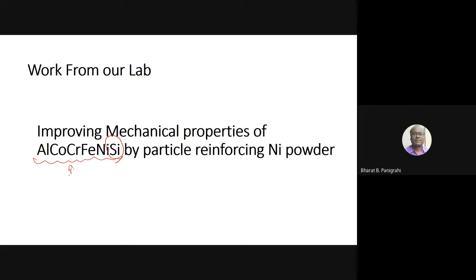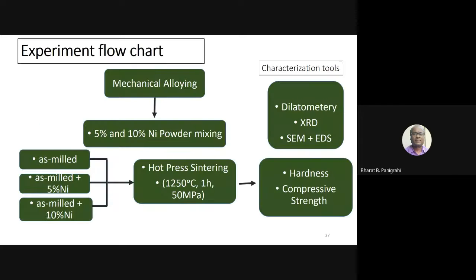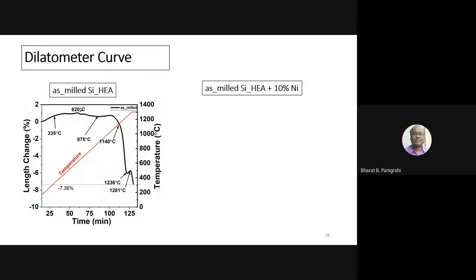The problem is, our goal was to improve ductility while exploiting the strength of this material. So what we wanted is to have this particular alloy and use some soft phase to provide ductility. Here we have used pure nickel as the soft phase, which is expected to provide ductility, where the strength comes from the high entropy alloy phase. So this is basically a two-phase mixture we are designing so that you can have both high strength as well as ductility. This is a typical powder metallurgy route, nothing wrong in that.